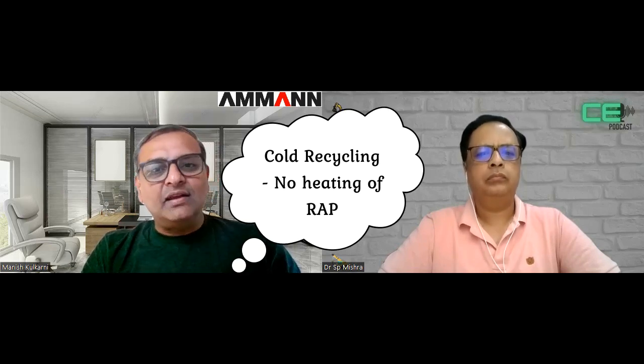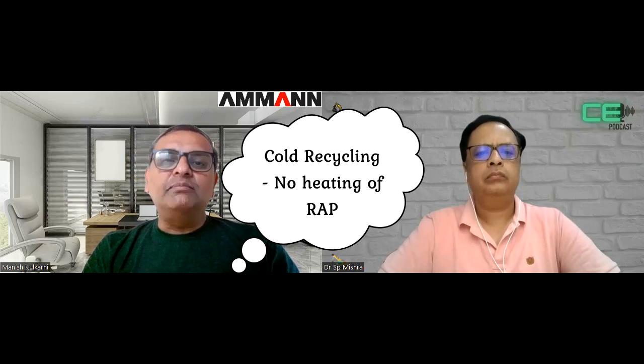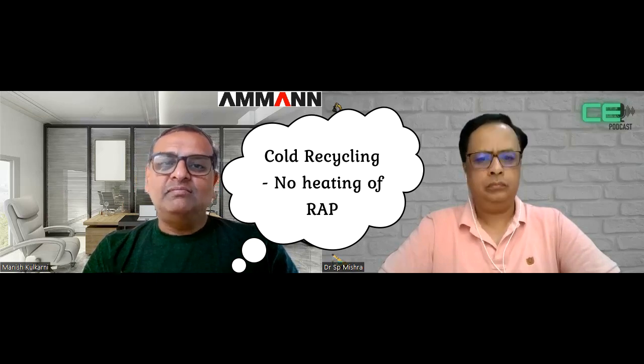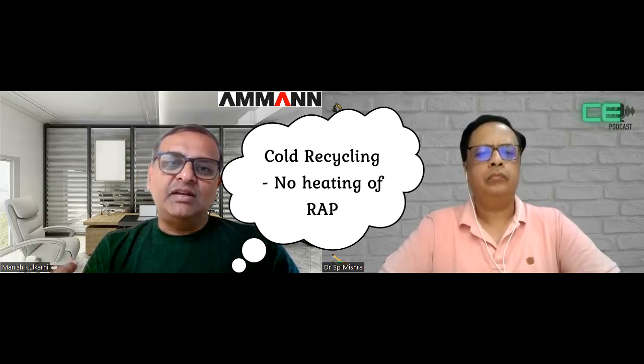So you can do a cold recycling, which means that you don't need to heat up the recycled asphalt material. You just pour it into the mixer, the current mixer. The 75% material comes from the virgin side, and then they are mixed together to form the homogeneous mixture. But as you go beyond 25%, you need to heat up the existing RAP material because it's difficult to extract the bitumen from that. And of course, 60% becomes even tougher, where you have to really do a warm RAP heating to make it adaptable to the existing virgin material and mix it together and make it homogeneous.